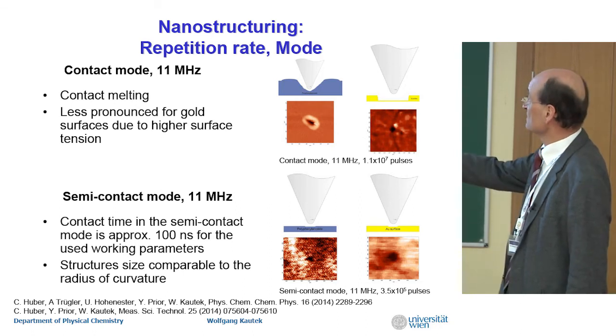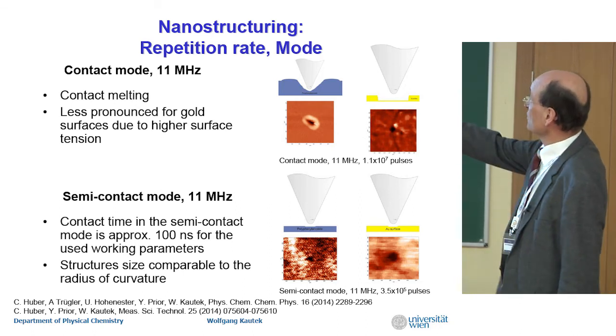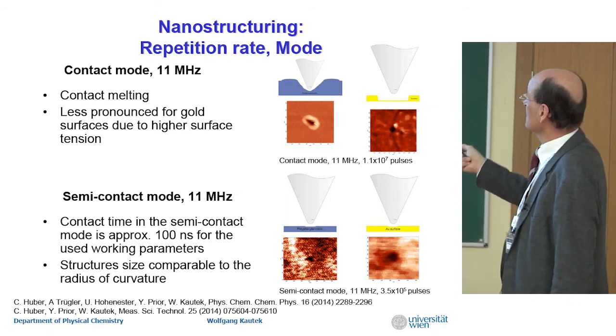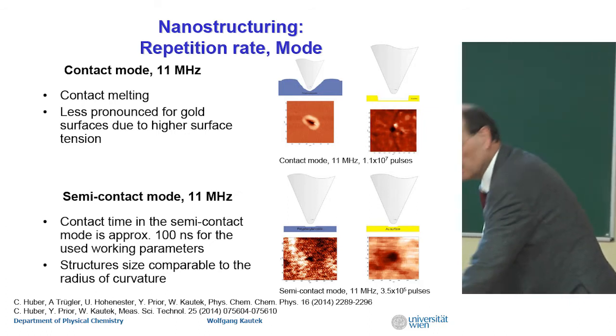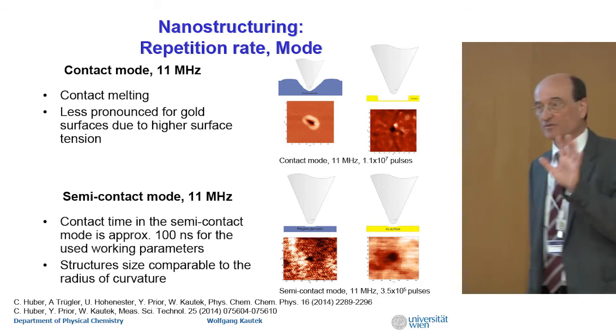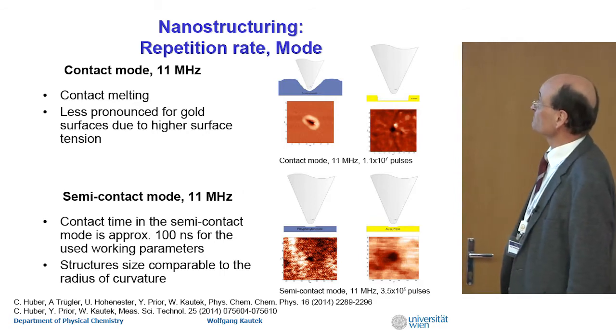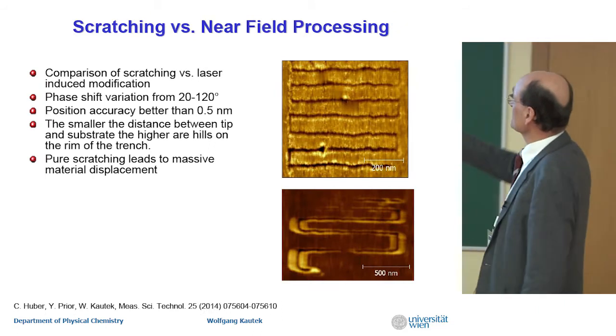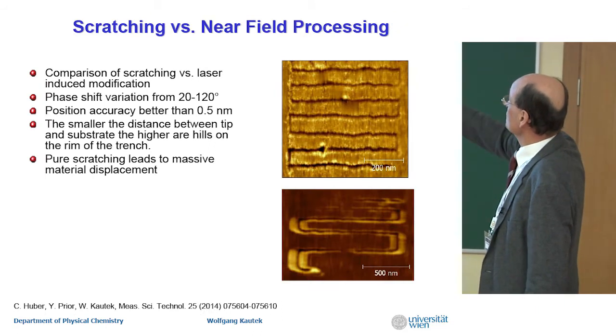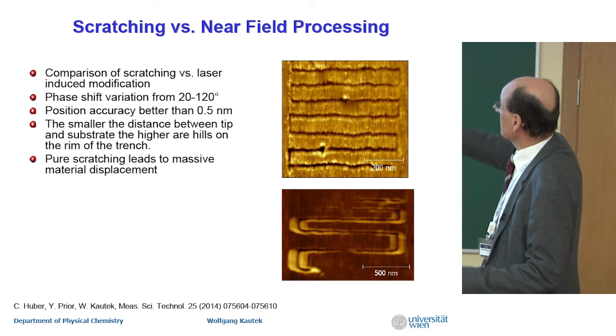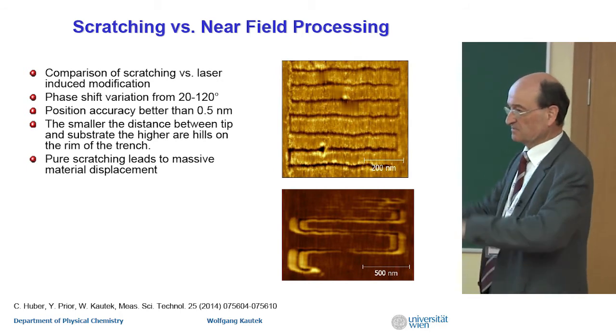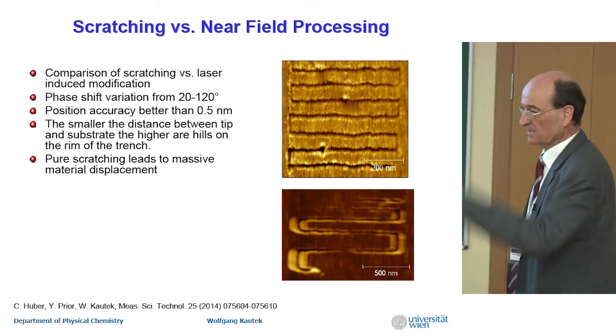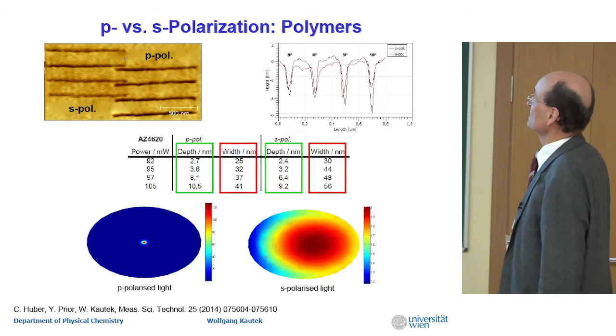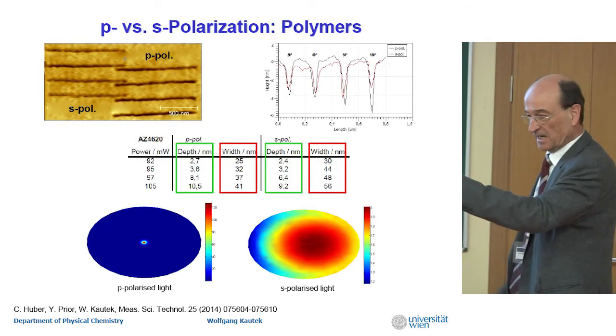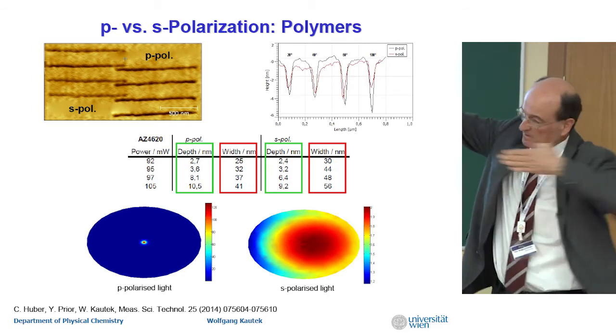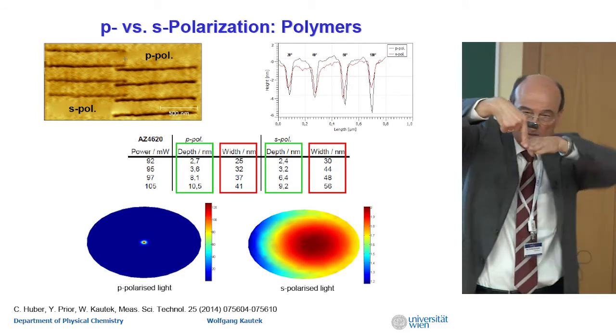It works, even with a high repetition rate laser. And with a low repetition rate laser, again, even in the contact mode, we do not get melting structures. So these are our first results on this. And of course, always the question is, do we scratch? Do we have field influence? Yes, there we can change that by the distance and the contact time and so on. And also the polarization of the tip, P or S, P or S.